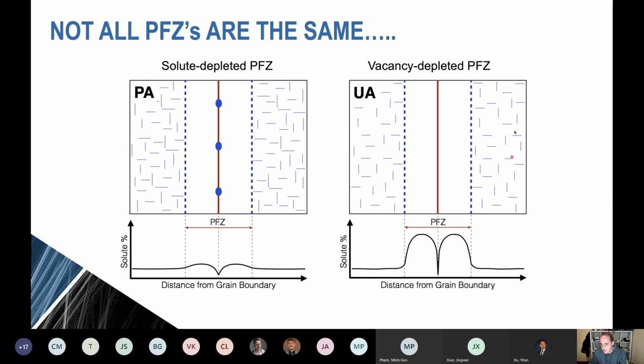So you might have precipitates out here in the bulk, you've got no precipitates here, but you do have solute left in the boundaries. Now, as you age for longer times, slowly that solute will get to the boundary, it'll form grain boundary precipitates, and then you have a solute depleted precipitate-free zone as well.